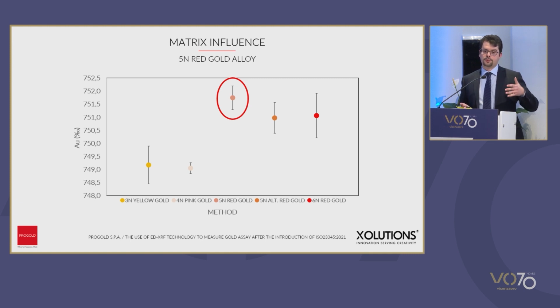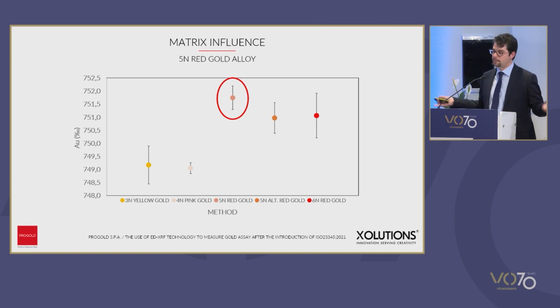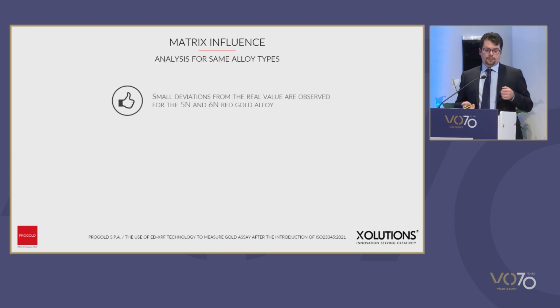You see that in the case of alternative methods, where we have a composition which is pretty similar, and with a large quantity of copper, we have good results, although they are not perfectly in line with the results achieved with the specific test. While as we go towards pink or yellow gold, we will find those big differences that we had found in the previous test. So what can we deduce?